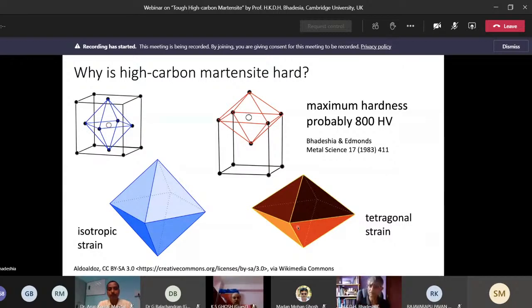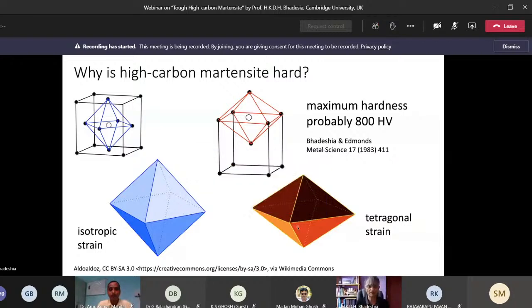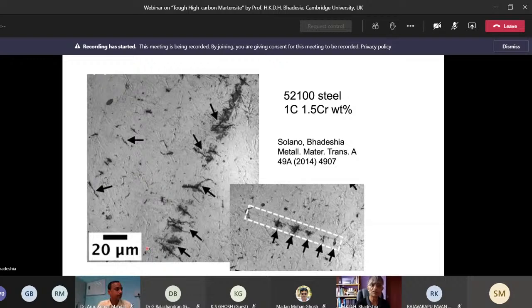Now, I explained to you that the consequence of getting this enormous hardness is that you will have very little plastic flow, and therefore the material will tend to be brittle. If you look at this image, which is not etched, here you can see a martensite plate, and there's another one over here, in a 1 weight% carbon steel, and the plate of martensite is full of microscopic cracks. You can see that it's cracked every so often along its length, and here's another image showing that. So immediately after quenching, you already have a lot of microscopic cracks in your material.